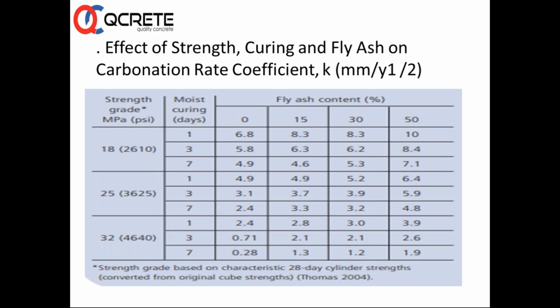And also the carbonation is said to be not an important point when you are significantly reducing the water cement ratio and making a concrete of a higher grade. At later ages, the concretes can give carbonation levels similar to control or better over a period of time, so it is not a problem. So if you are blending higher amounts of fly ash in concrete, one of the most important things we need to do is reduce the water cement ratio and go for a slightly higher grade of concrete, which can give higher strengths at later ages to have comparable carbonation levels.